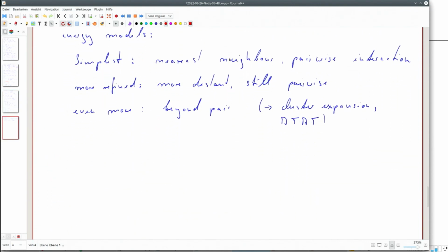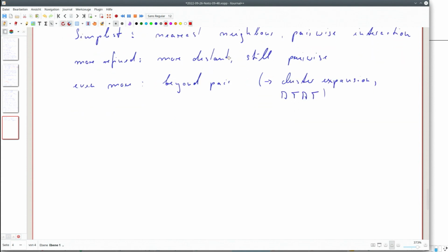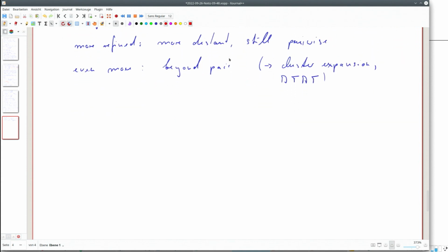So when we say Metropolis, we mean the transition probability algorithm that is given by A. How you choose to exchange is where Glauber, Kawasaki, all this come. Second thing, even in the case you are using EAM potential, for example, you don't calculate for all because there is a cutoff distance. You are using LJ, there is a cutoff distance. So even in an off-lattice, when you do more complicated energy, it is never the full system energy. Even if I randomly exchange, it's only the region where energy will change.